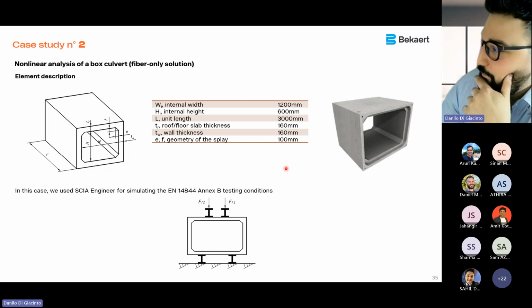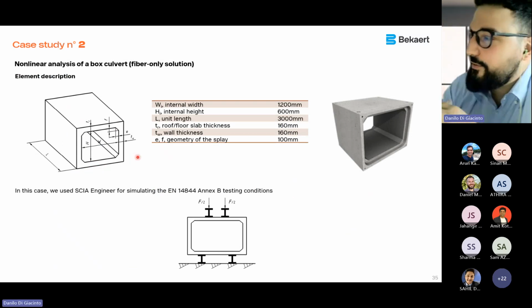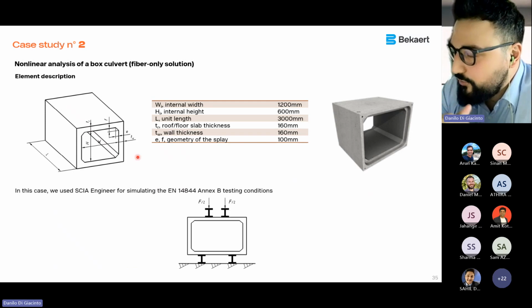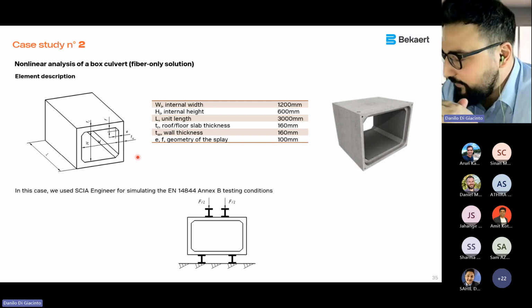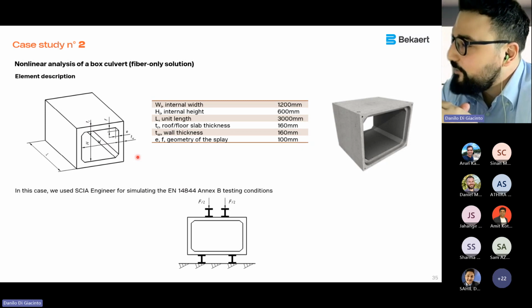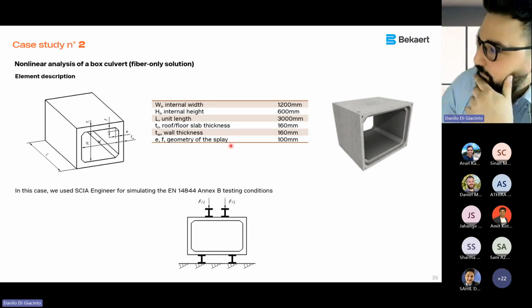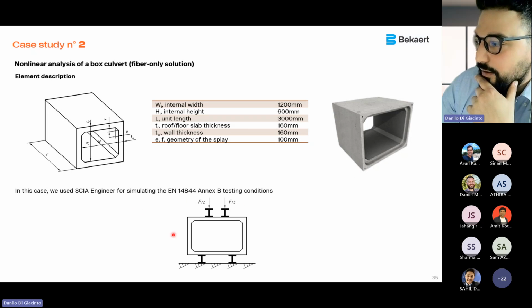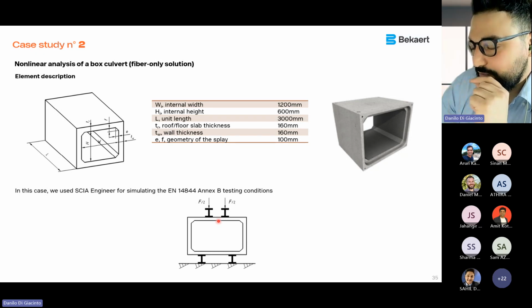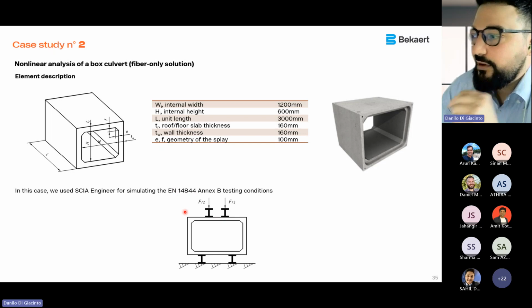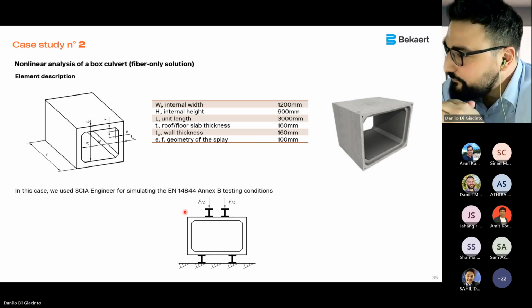Case study number two. This is a box culvert. Again, fiber-only solution, 25 kg of 5D 65/60 GG galvanized fiber. This is a box culvert in Belgium. The box culvert is 1200 millimeter wide, 600 millimeter high, and the test to assign the load class and to achieve the requirements are given by the European standard 14844.